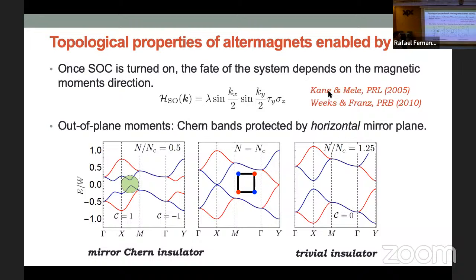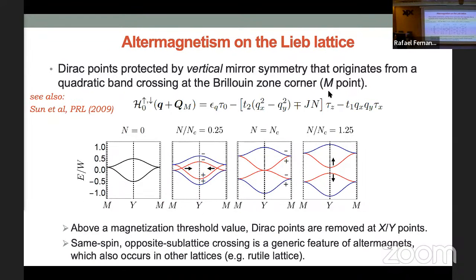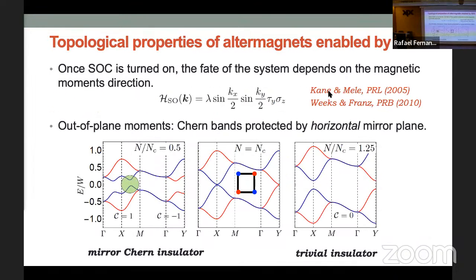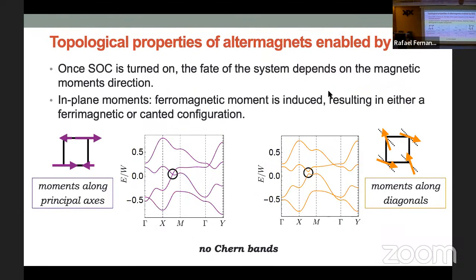If the moment, however, points in-plane, the situation is different. As I start increasing the size of the magnetization, remember what I showed here is that I have this and then this disappears. In the same way, I go from a topological insulator with a mirror Chern insulator to a trivial insulator just by changing the size of the magnetization. And as I mentioned, and just to finish, if my moments are in the plane, this is gone. I no longer have Chern bands, because in both of these cases I actually mix with an in-plane magnetic moment, and I get either ferromagnetism or canted ferromagnetism.